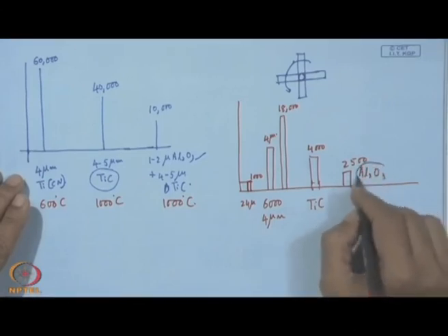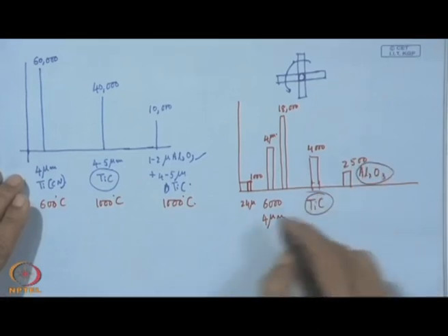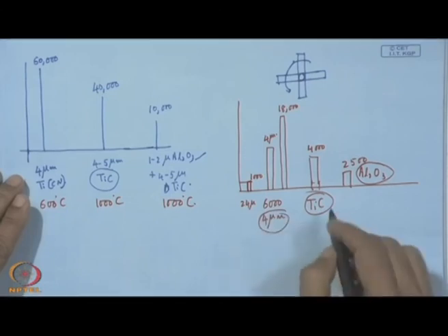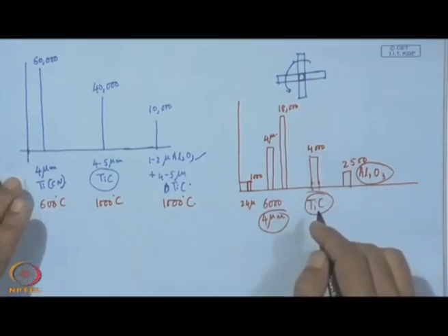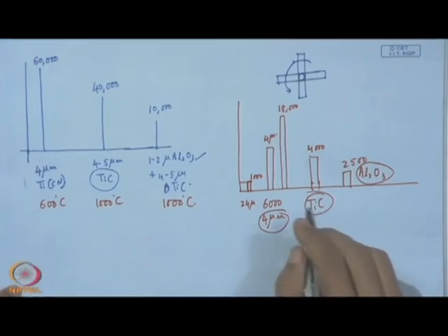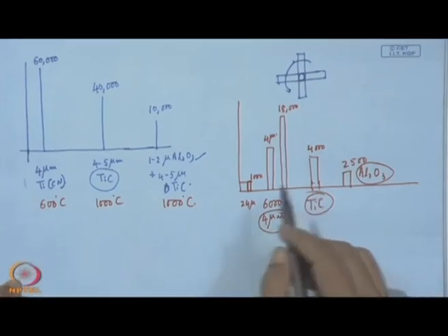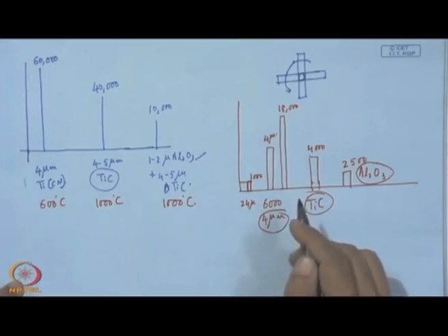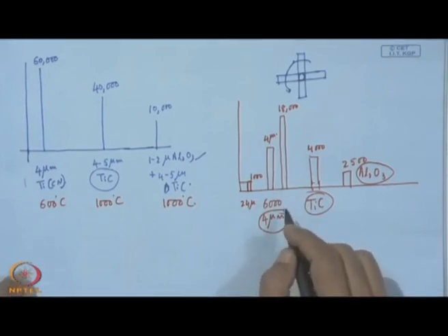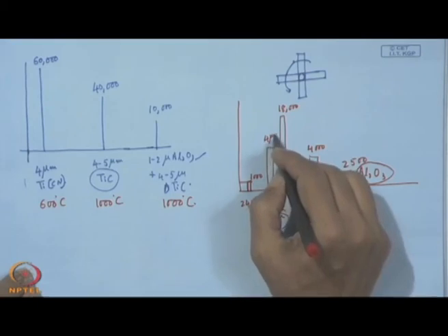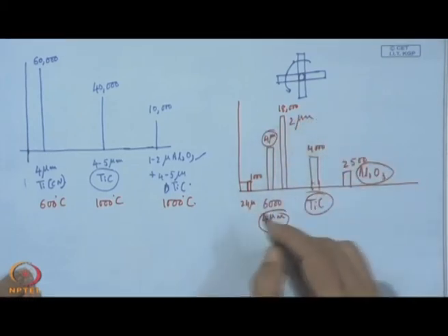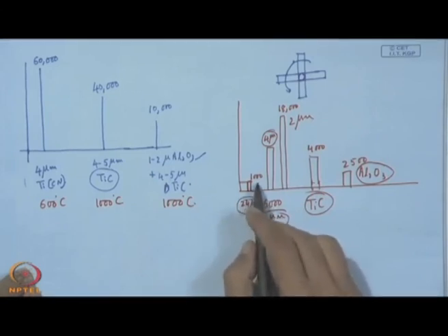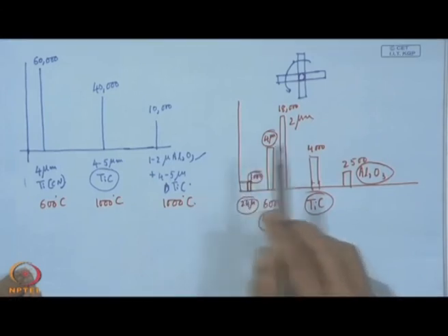So, this is a high temperature coating and this is a low temperature coating of equivalent thickness, but when these inserts are used in milling action with a fly milling mode, then also this low temperature coating shows its strength. This is at 4 micron, but when it is 2 micron it is 18,000, and when it is 24 micron it is very low, 1000.